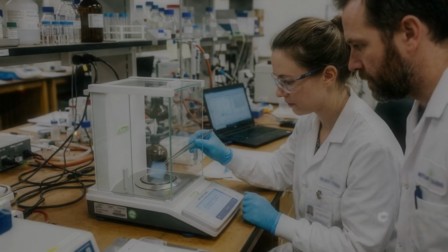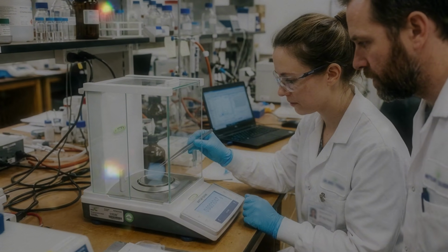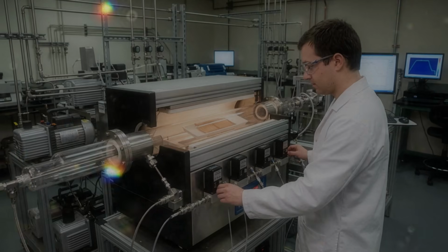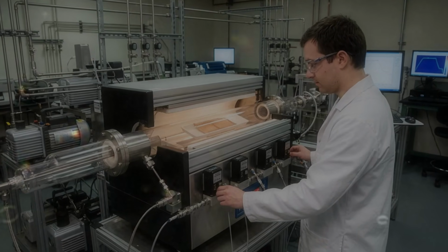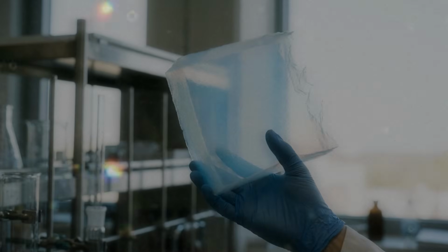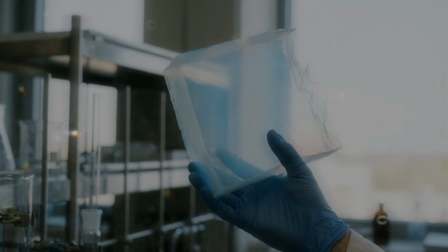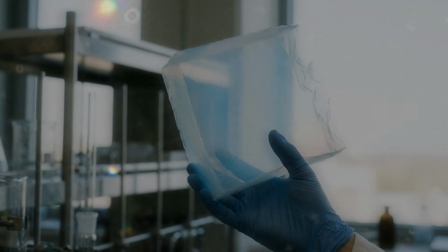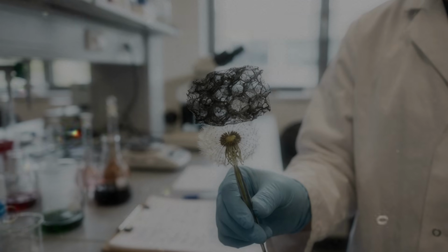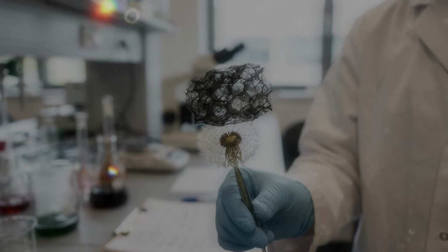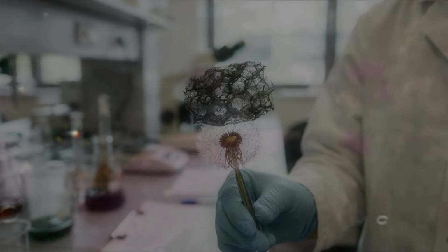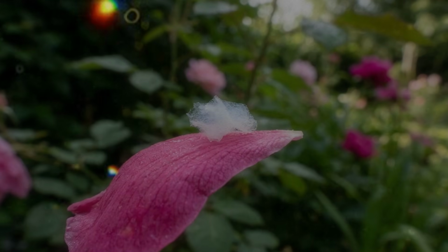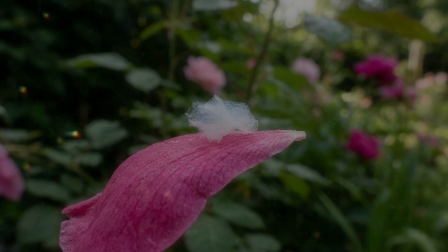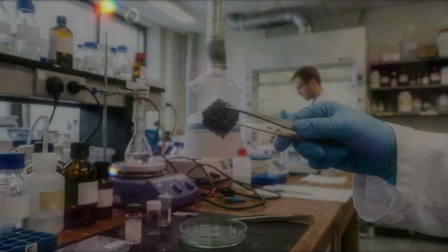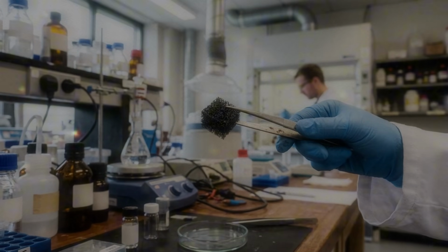The ability to absorb light can make heating faster, which is useful in some devices and dangerous in others. A black carbon aerogel placed near intense radiation may become hot even when the surrounding air remains cool. Every unusual ability therefore arrives with a condition. Aerogel slows heat, but not under every temperature and pressure. Aerographene conducts electricity, but only when enough pathways remain connected. It recovers after compression, but repeated cycles cause fatigue. It reduces sound, but performance depends strongly on thickness and frequency.